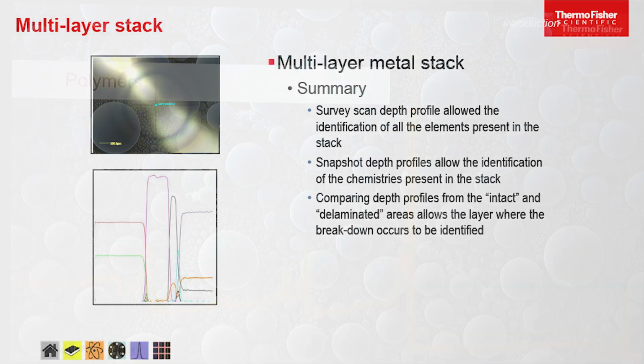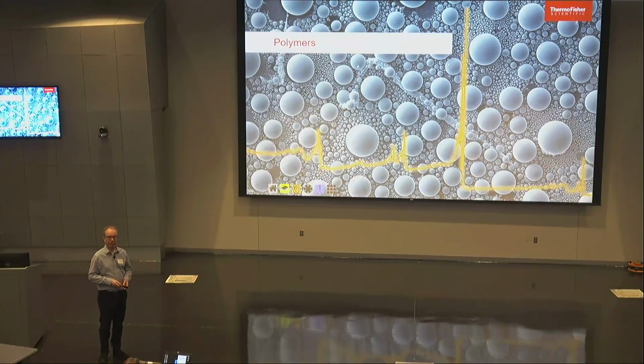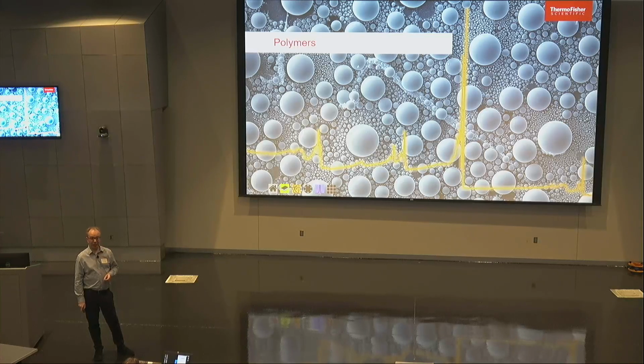Yes. Depth profiling, how do you get a sense of how deep you've actually gone, and how do you control that you're not sputtering your material? Well, we are always sputtering the material somewhere else, so it's a good point actually that you do have to control the way that your system is aligned and arranged so that you're not directly sputtering the material off the sample and coating some other part of the instrument. Generally, because you're removing quite small amounts, the particles are just pumped away through the vacuum system, so we don't see them building up somewhere.